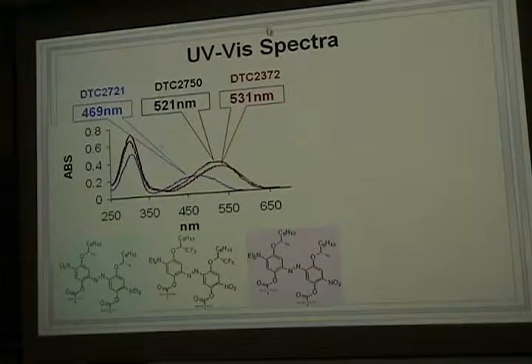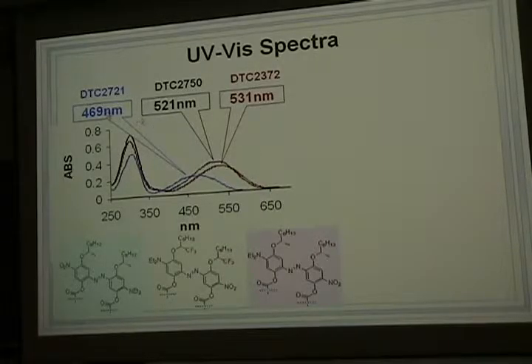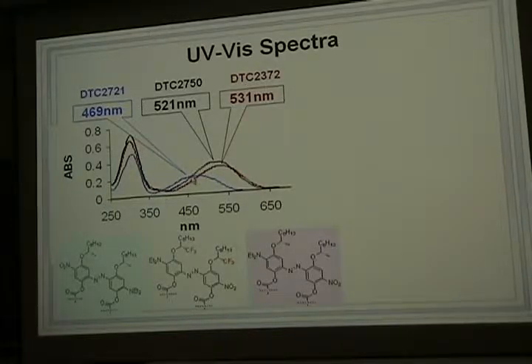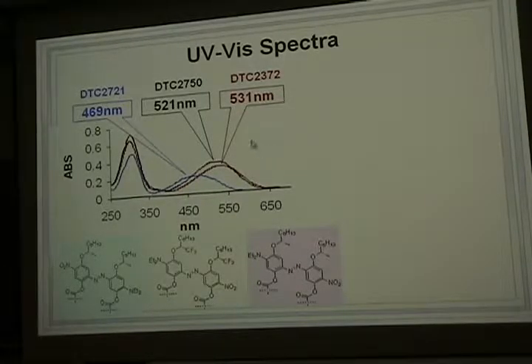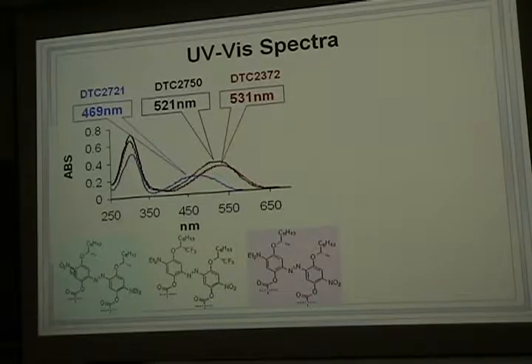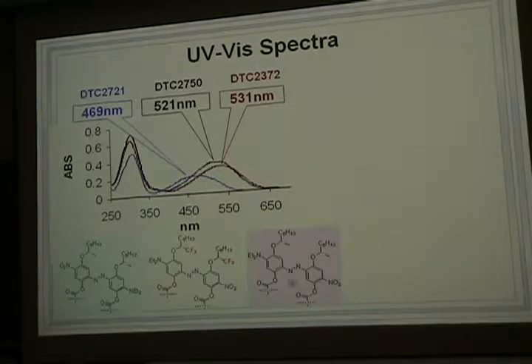We also measured the UV-vis spectrum of three chromophore materials — DTC2721, DTC2750, and DTC2372. As you can see, if you compare this compound with this compound, the maximum absorption wavelength due to the charge-transfer band was shifted more than 60 nanometers to the blue. We think we can understand why there is this big shift. Look here: in this group, the strong electron-withdrawing group is attached to the donor group, which decreases the electron-donating ability of this compound. That is why we observe a blue shift compared to this compound.